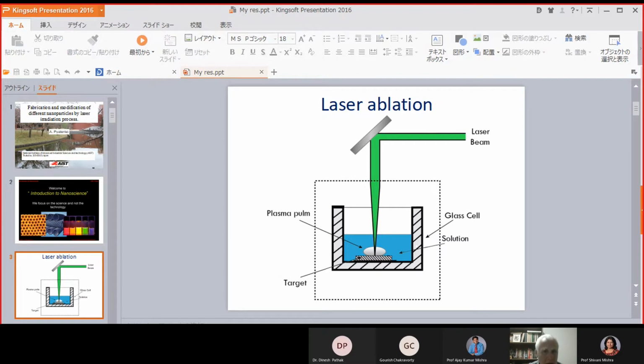Okay, next. We try to use the previous result, the nanoparticles produced by chemical synthesis, and try to ablate this solvent with our laser. After 1 hour of ablation of this colloid, we produce this rather good result. You see, now we observe only small particles, and the particle size is characterized by a very sharp size distribution. Average size is about 3 nanometers, plus minus 1. Here is the histogram of the particle size distribution. So we produce a very good result.